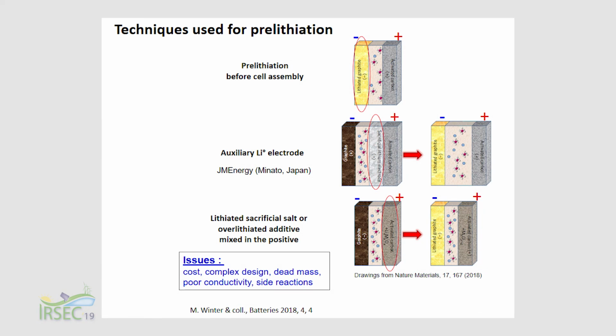And now, for pre-lithiation, three main techniques are developed. One technique is to pre-lithiate the negative electrode previously to the cell assembly. It makes one extra fabrication step. There is another technique which consists in adding an auxiliary lithium metal electrode in the lithium-ion capacitor. And this is already commercialized by JM Energy, a Japanese company. So that's quite interesting. And the other technique, which is most studied at the moment, and Carl has given some example, is to use some lithiated additive that you put in the composition of the positive electrode. Upon the first charge of the cell, this additive will provide irreversibly electrons and lithium ions to the negative electrode.